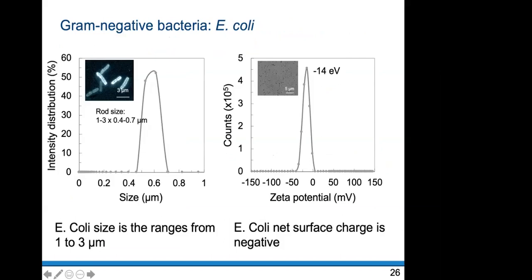So here, this is the gram-negative bacteria I used as a model system, which is E. coli, a very common bacteria that is used in microbiology. The one that I used is of micrometer size, because as I mentioned, we are more interested in using micrometer size bacteria. It is 1 to 3 microns in length and 0.4 to 0.7 micrometers in diameter. And they have an overall net negative charge on their surface.